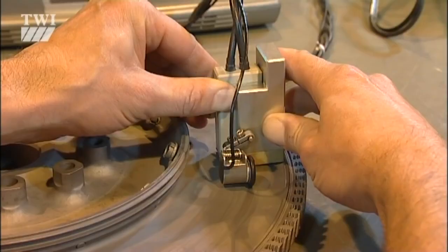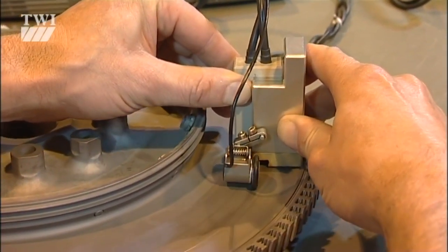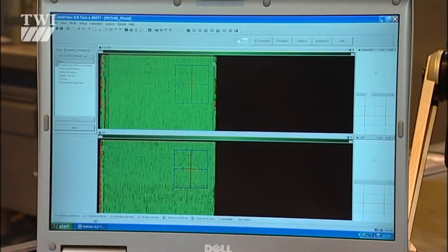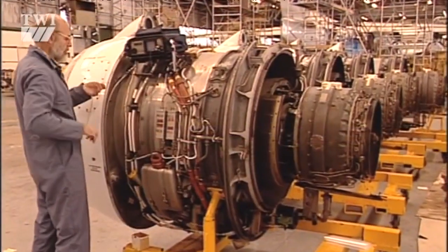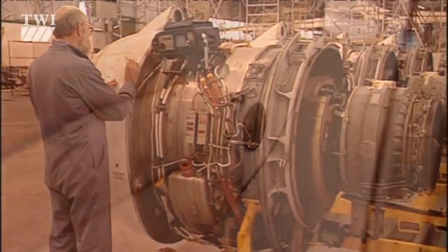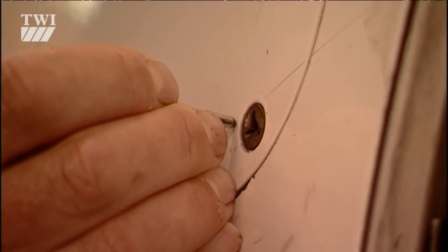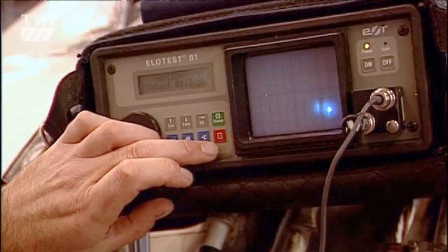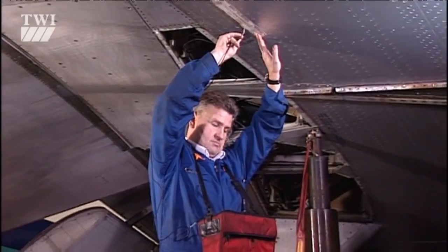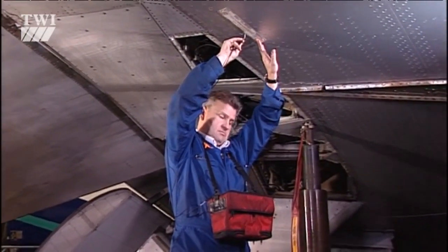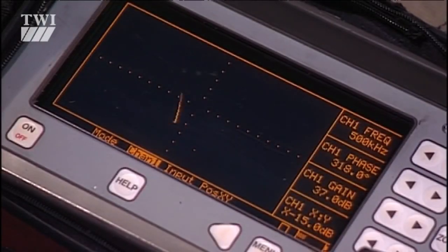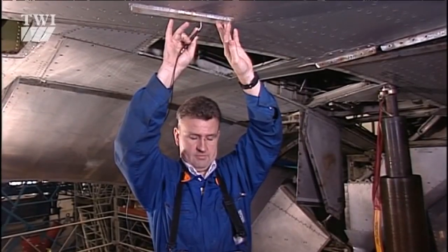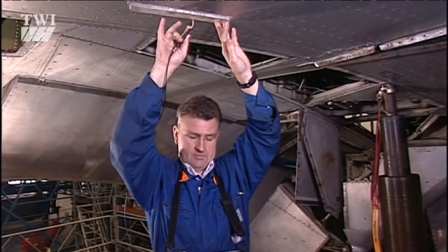It's useful for detecting surface breaking or near-surface cracking and variations in material composition. Eddy current methods are used for surface inspection of both non-ferritic and ferritic materials. Eddy current penetration is deeper on non-ferritic materials, so it's also used for special applications with thin components, such as in the inspection of multiple layer airframe components for cracking or corrosion thinning.